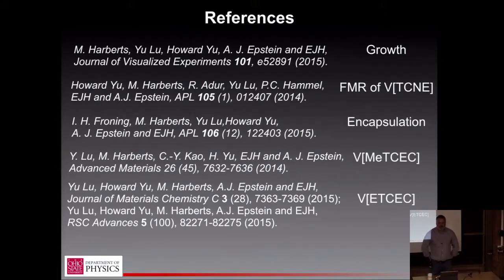And what's the problem there? That's a good question. Have you done an experiment? Just no damping, or... I'm not convinced that that's a great measurement. For example, putting it on top of a high spin orbit material versus a low spin orbit material. There's enough questions about how the material grows that even if the line width changes, I wouldn't be convinced for our material at least.